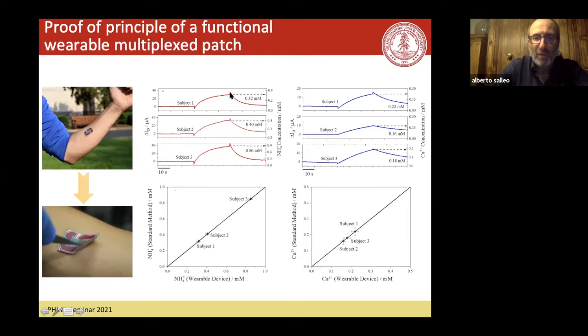And then after you build the calibration curve, this change in current can be translated into a concentration of ammonia. And to make sure that our measurement is correct, we then measured the concentration of ammonia with a standard electrochemical electrode, and our measurement after the calibration is just about as good.